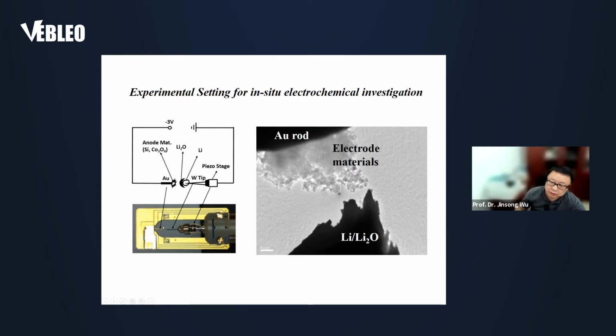On the other side, there is a tungsten tip. And on the top of the tungsten tip, by scratching, metal lithium covered with lithium oxide can be loaded on the tungsten. And then the tungsten wire is driven by a piezo stage. So this wire can do very fine movement inside the TEM.